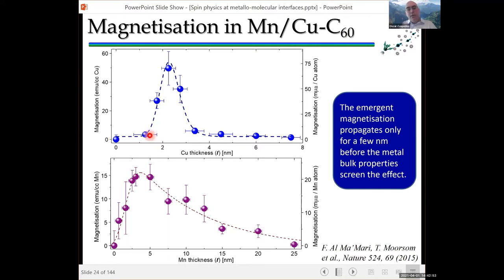Manganese is closer to the Stoner criterion, is paramagnetic. The effect we saw will extend farther, but it will be smaller. So the induced magnetization in manganese was smaller, even though we could see it for thicker films.